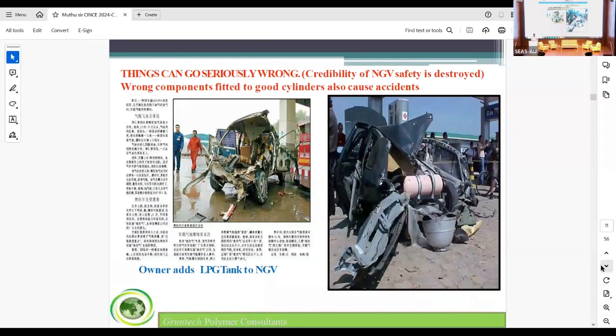Even good cylinders, if you fit a wrong component, can have problems. One technician asked me, shall I put this LPG kit on the CNG cylinder? In one of the trials, our technician in Thailand fitted the valve too tightly, so the pressure release device didn't work when we did a bonfire test. It didn't burst on the other side.